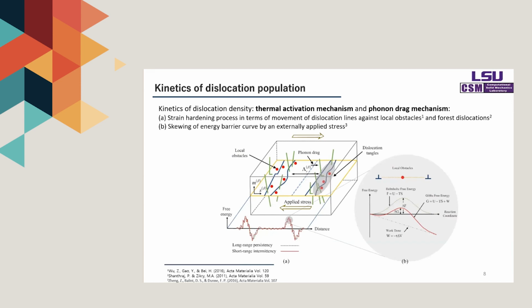The flow rule is based on the Orowan equation. The flow rule describes the kinetics of the dislocation population, such as the thermal activation mechanism and drag mechanism. The critical resolved stresses are a function of GNDs and SSDs.